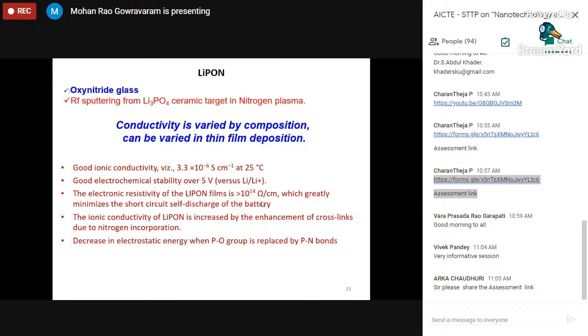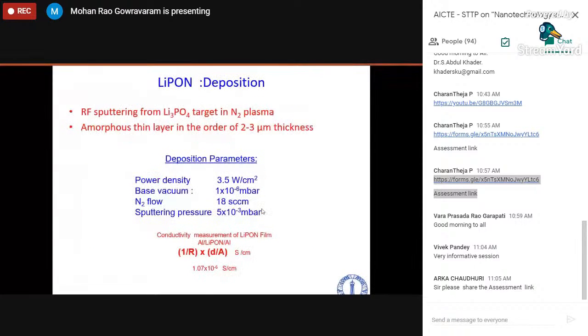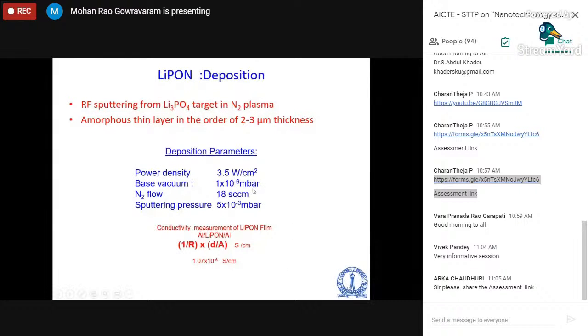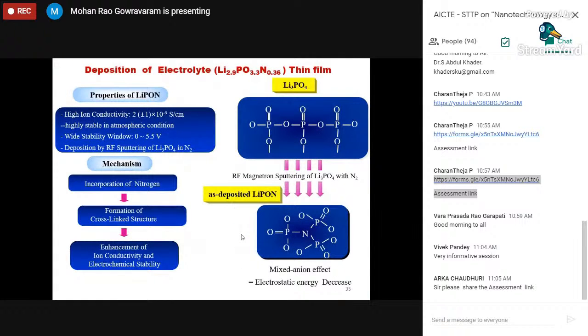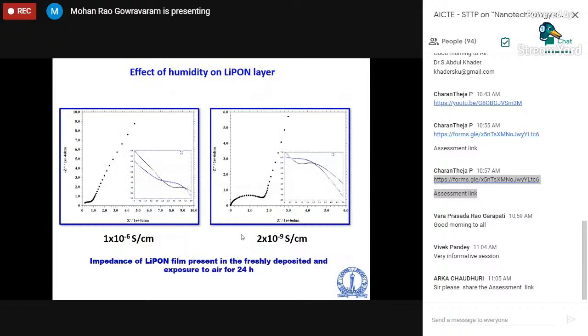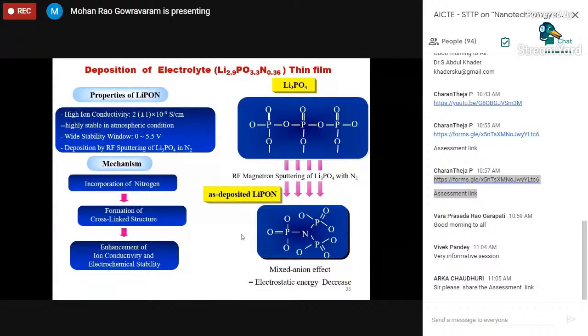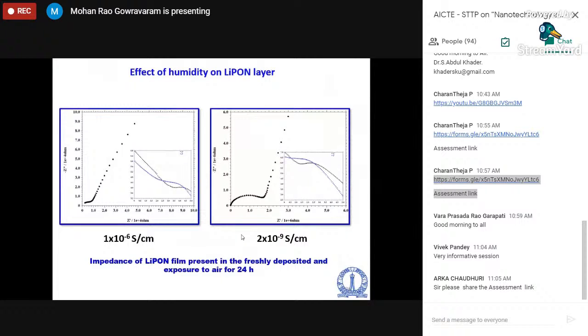How you sputter this one is that you take a lithium phosphate target, Li3PO4, and sputter in nitrogen plasma. You sputter at a certain power density and other conditions, and then you deposit a thin film of lithium phosphate, LiPON, and then you see whether nitrogen has gone in, because unless nitrogen goes in the required quantity, it is not an ionic conductor. So you do an XPS and find out that nitrogen is there, and then you test its electrochemical impedance to measure the ionic conductivity. By optimizing the parameters, you get 1 × 10⁻⁶ Siemens per centimeter, which is close to its bulk value.